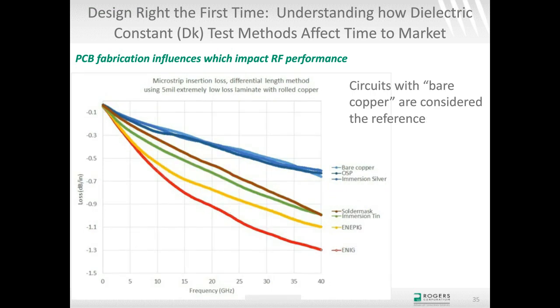And what I'm showing is, to begin with, the light blue curve is the bare copper circuits, and they are considered the reference. And then you can see there's some other blue curves there as well, and I kept them nearly the same color to basically say that all these circuits behave the same. And that is circuits with bare copper, circuits with OSP, and circuits using immersion silver. I really don't see a significant difference in losses of those three. And then solder mask is the brown curve, it looks like. Immersion tin is green, yellow is ENEPIG, and red is ENIG.